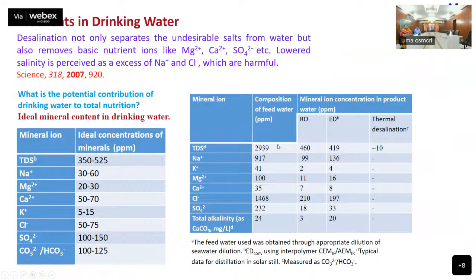So we have made a synthetic solution of 2939 with the following ion specification. Then we have desalinated the water by RO and by ED, and we have purposely reduced the pressure for the RO process. We have run the ED process, and in this case, we have modified the electrodialysis membrane, the polyethylene interpolymer membrane, with polyaniline, so that we have tuned the transport phenomena of chloride and sulfate, so that sulfate can be retained and chloride can be removed easily.